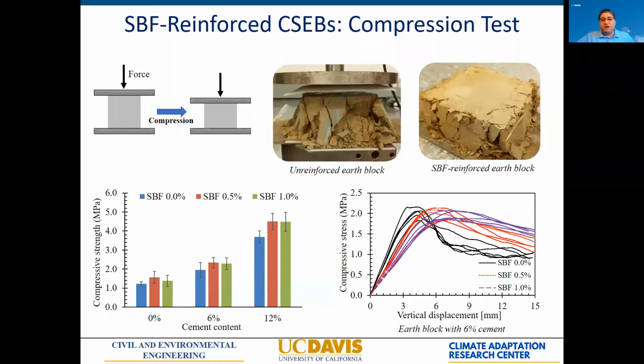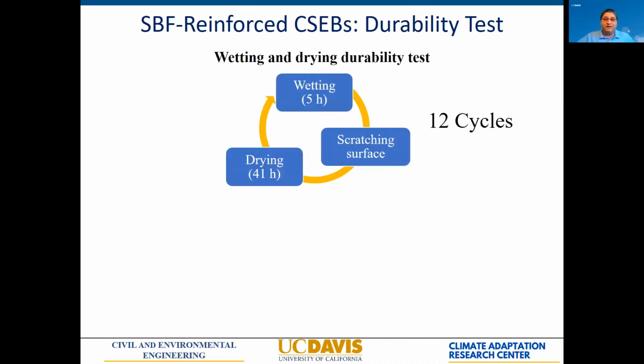We needed to be careful in the amount of fibers that are added to the material because while we are increasing on one side the compressive strength and the ductility, we are also reducing the durability, which we tested with the wetting and drying durability test cycles.